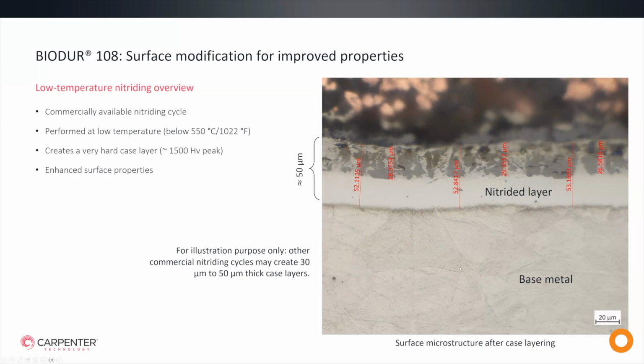And once again, for those of you who have not reviewed the patent or are not familiar with the process, nitriding is just a low temperature process that diffuses nitrogen into the surface, which can create a very hard case layer of like 30 plus microns. And that's dependent really on the exact process, the base material, and the processor themselves. In our test, we were able to identify a hardness of approximately 1,500 Vickers at peak, which roughly converts to just above 70 HRC. There's not a great scale because 1,500 is actually beyond that.